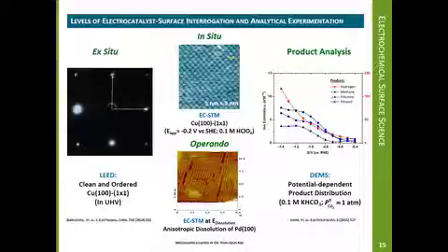In this example, differential electrochemical mass spectrometry, or DEMS, is used to combine voltammetry with mass spectrometry. DEMS has the unique ability to provide online and real-time product identification of volatile CO2 reduction products. The product distribution can be expressed as a function of applied potential to the copper electrode. A direct atomic level image may then be obtained under solution in an electrochemical cell at an individual applied potential under constant potential control. For model systems, the same electrode may be removed from the electrochemical cell at that potential and interrogated in vacuum conditions by surface-sensitive spectroscopies.